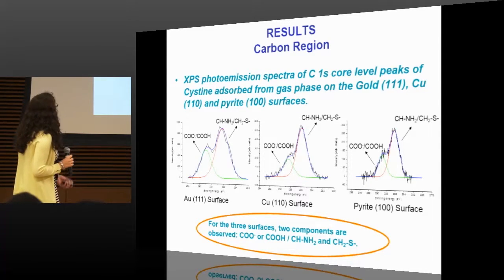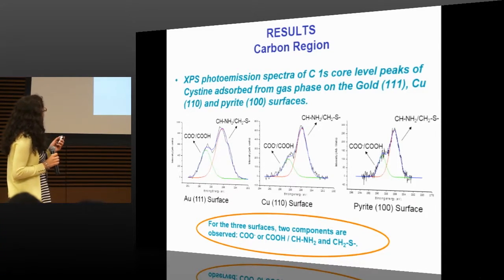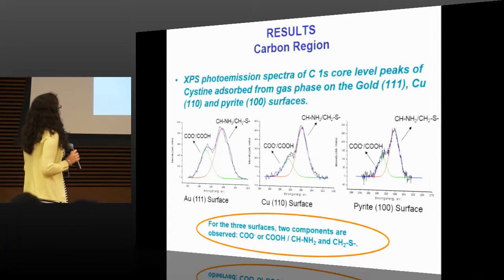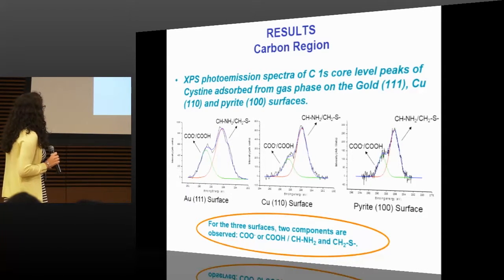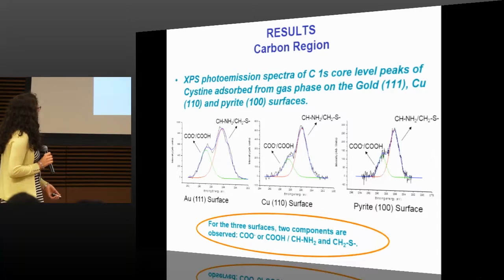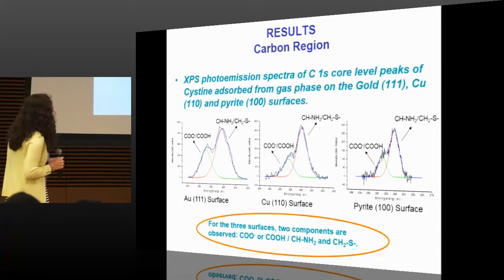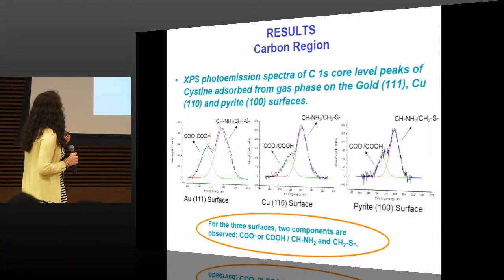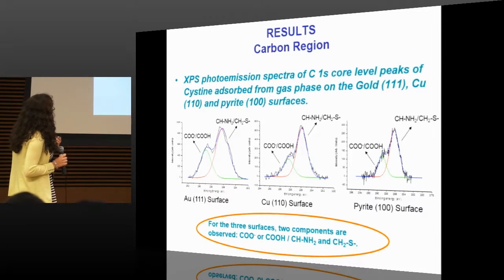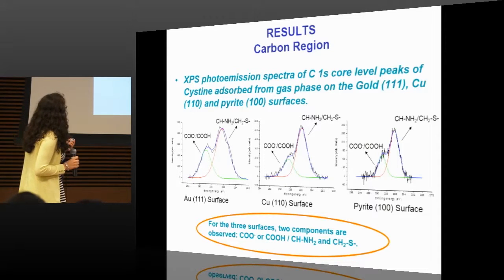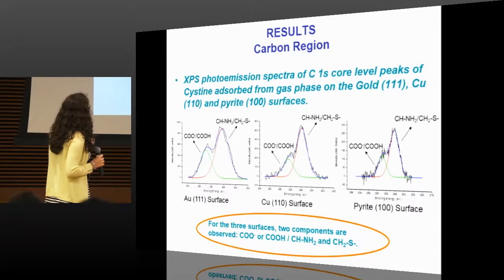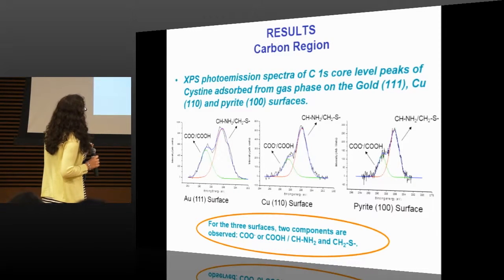In this slide, you can observe the XPS photoemission spectra of carbon 1s core level peaks of cystine adsorbed from gas phase on the gold, copper, and pyrite surfaces. For the three surfaces, two components are observed. The higher binding energy component is a carboxylate or acid group. The other component is carbon joined to the amino group and carbon joined to the disulfide bridge.